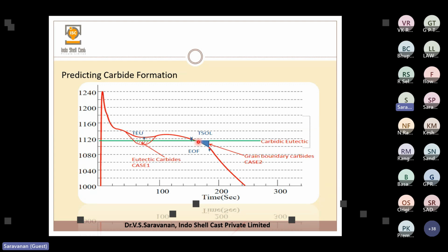And then here the graphite eutectic line is here, T solid is here, and the end of freezing is here. If this particular region is very close, then it is good. If the end of freezing increases to more than 50 degrees, then low melting alloy segregation at the grain boundaries is higher, and we will get grain boundary carbides. This particular area is calculated indirectly in the software, and they give the possibilities of getting grain boundary carbides.